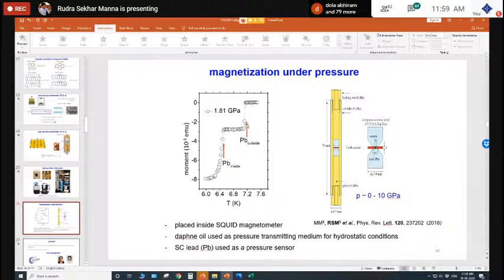This is the superconductor transition of lead. And then you can apply pressure like 2 GPa, then you can shift the transition to a lower temperature, around 6.5 Kelvin or so. So that means instead of lead, you can put some other materials which you are interested in, then you can tune this material, you can go from one phase to another phase.